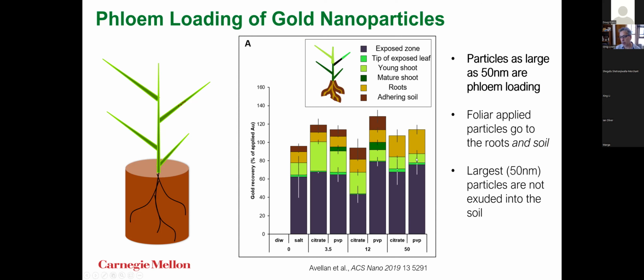And what was interesting to us is even 50 nanometer particles were making their way down to the roots. That was way bigger than we thought. Our 50 nanometer particle was the one we thought wouldn't go anywhere. It was going to be our largest size, our cutoff, but it turns out that they moved down to the roots just fine. They don't exude into the soil, interestingly. So there is some cutoff between 12 and 50 for that exudation out of the roots. But this was kind of an interesting find.